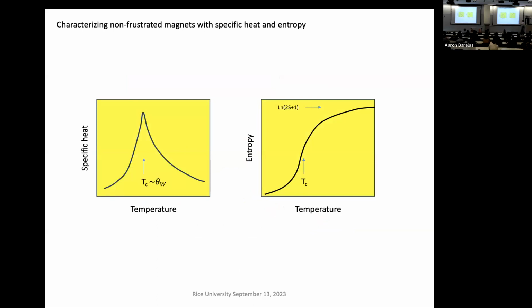Characterizing non-frustrated magnets with specific heat and entropy. Typically, if you measure specific heat, you'll find what's called a lambda anomaly, because it looks like a Greek letter lambda, with the peak that occurs at the ordering temperature. And the entropy that comes out will look like this. You'll get ultimately R log(2S+1), with half the buildup at Tc.